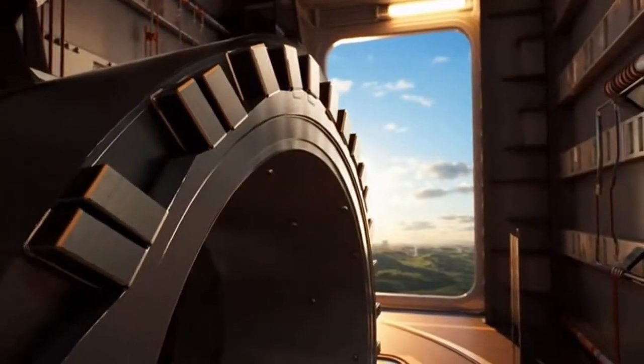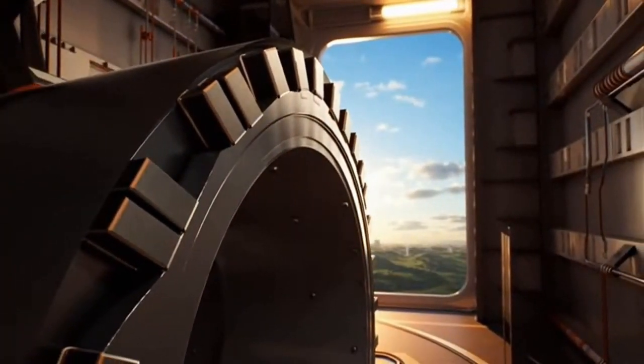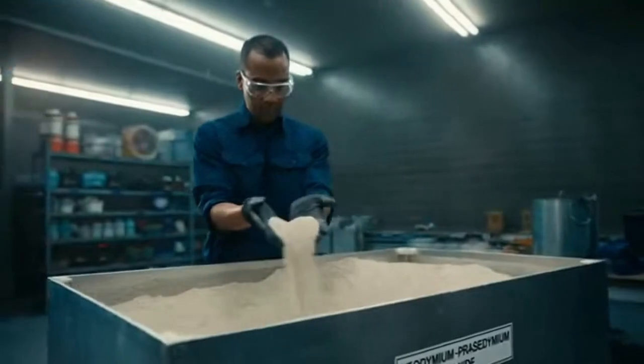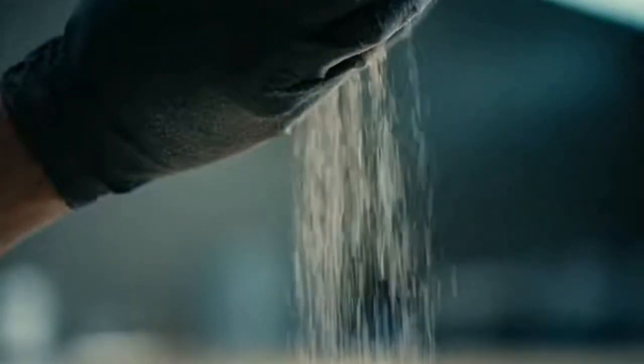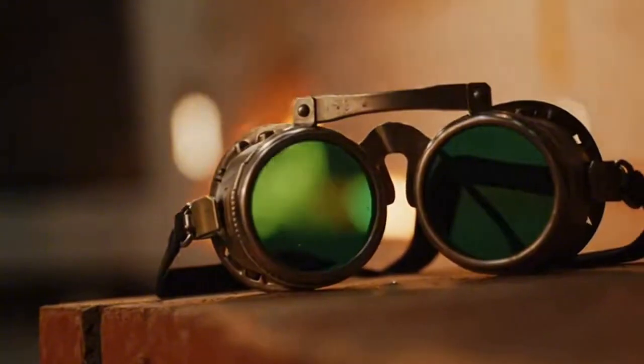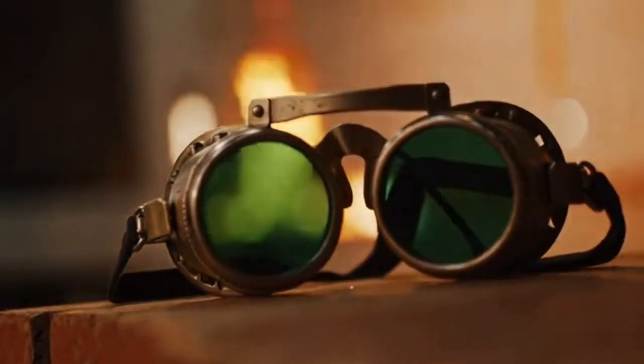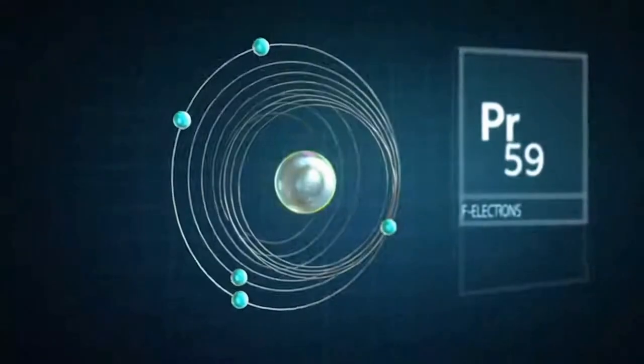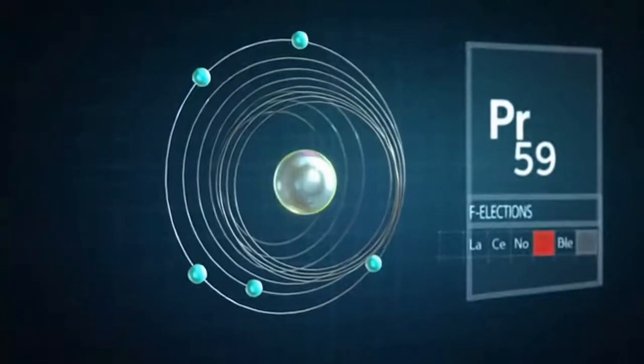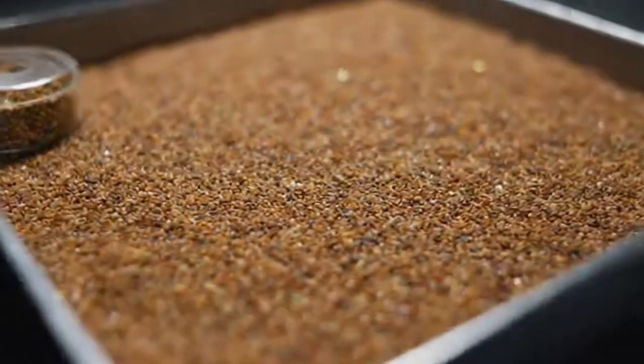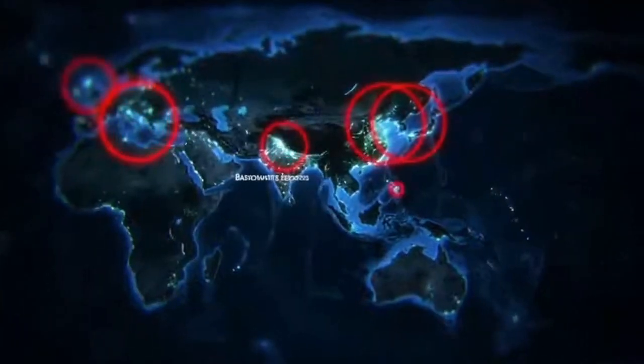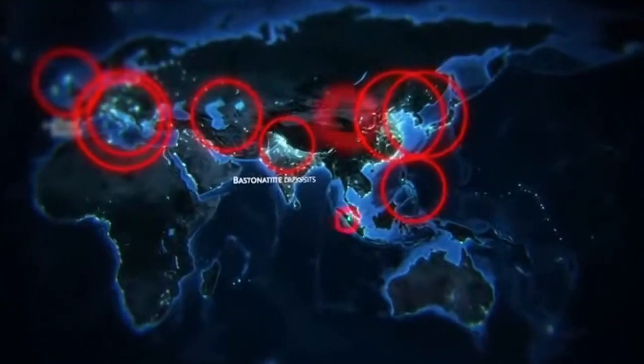Those knobs, grain size, diffusion of heavy rare earths at grain boundaries, and which twin you favor, how praseodymium earns its rent. Praseodymium also wins a quieter race in glass and ceramics. A small amount of praseodymium in glass can transmit a precise red while swallowing yellows, which is magic if your job is to make a red glass that does not wash out in daylight.